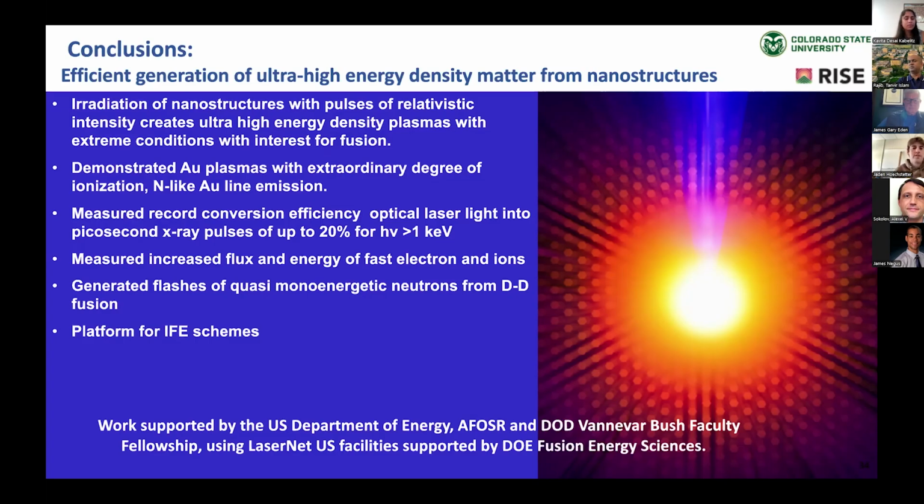We measured increased flux and energy of electrons and ions from the nanowire arrays as compared to flat targets, and generated quasi-monoenergetic neutrons from the DD fusion, and this can be used as a platform for IFE schemes.